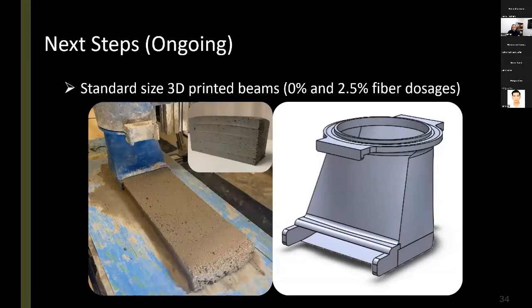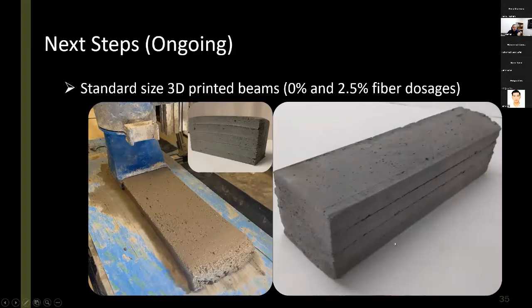In terms of the next steps, we want to basically use standard 3D printed beams to measure the flexural strength and ductility of these materials. So we had to spend a lot of time on the nozzle design and our extrusion system to be able to print these layers that you can see here. These are 4-inch wide, and we were able to print actually very nice and accurate samples.